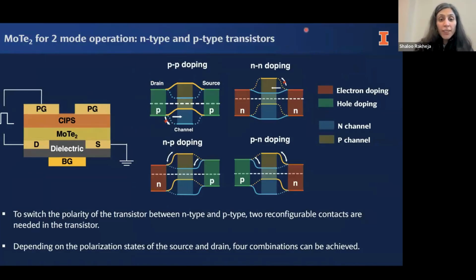So for a 2-mode operation, as I said, we can dope it entirely P. So that's great. This is a P-type transistor. We can dope the device entirely N-type, which is this device. But what we can do, because we have 2 separate programming gates on the top, we can program one of the contacts as N, one of the contacts as P, or vice versa. We can program the left contact as P, and we can program the right contact as N. What the bottom 2 does is it gives us a diode. So we can really have a forward bias diode or a reverse bias diode, and it can have very interesting photo responses. So we've actually taken this device and we shine light and we see what kind of photo response we get out of this transistor by doping the source and drain differently.